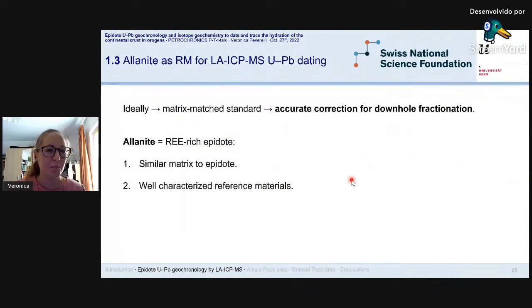And here we have our second problem, because LA-ICP-MS requires the use of a standard, and ideally we want the standard to have the same matrix as the sample. The reason for this is that during ablation, so as we drill down in our sample, uranium and lead are fractionated from each other, and the pattern of this downhole fractionation depends on the matrix that we are ablating. So for epidote dating, we would like to use an epidote standard, which does not exist. However, we may try using allanite as a reference material, because allanite is the rare earth element-rich member of the epidote supergroup. So we may assume that the matrix of allanite is quite similar to that of minerals of the epidote-clinozoisite solid solution that we call epidote.